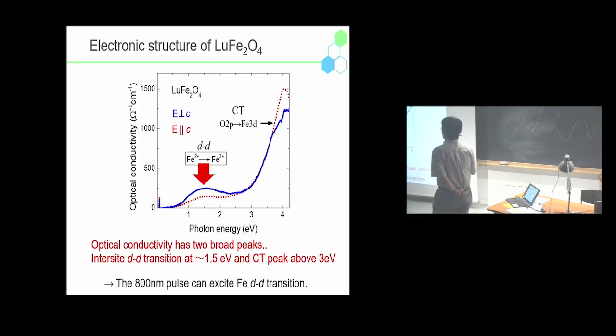Now, before showing the pump and probe data, I will show you the in-plane and out-of-plane optical conductivity of these materials. In both polarizations, you can see a broad peak at around 1.5 eV, 800 nanometers, and also a huge absorption above 3 eV. The former is assigned to the d-d transition between Fe2+ and Fe3+. The latter is assigned to the CT transition, charge transfer excitation from oxygen 2p to the Fe3+ sites. As I told you, we chose this 1.5 eV, 800 nanometer light as the pump light, so the pump light can excite the iron d-d transition.